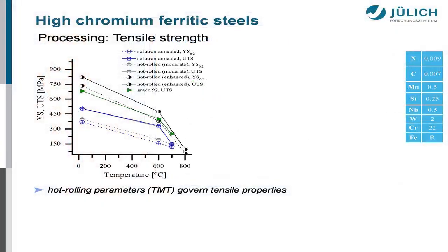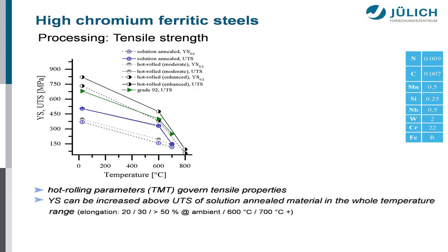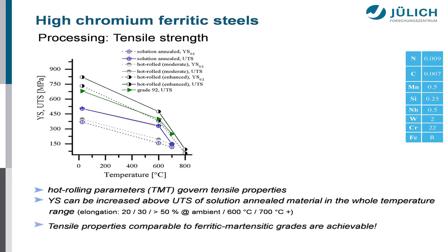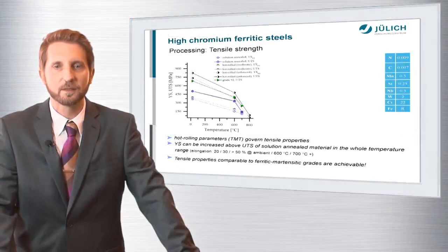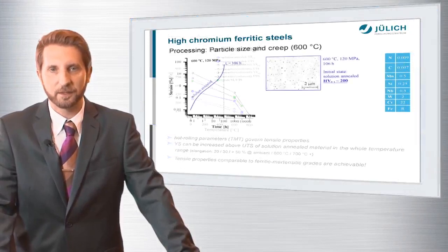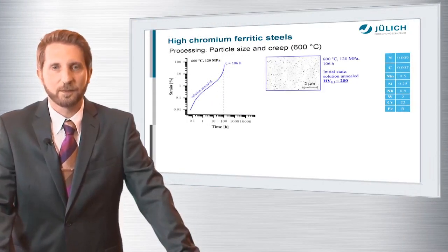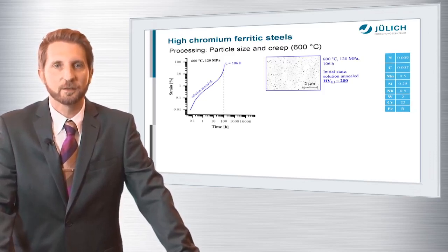So coming back to tensile strength, again, doing the benchmarking against the martensitic grade 92, you can see here that by changing the hot rolling parameters, the yield strength of our high chromium ferritic steels can even be tuned beyond the ultimate tensile strengths of ferritic martensitic grades. And this can be done over the whole temperature range with still sufficient and reasonable ductility. And the takeaway message is the tensile properties we can reach in our fully ferritic grades are comparable to ferritic martensitic grades. Processing, thermomechanical controlled rolling, does not only affect short-term tensile properties. It has a strong impact on particle microstructure, and for this reason for creep performance too.